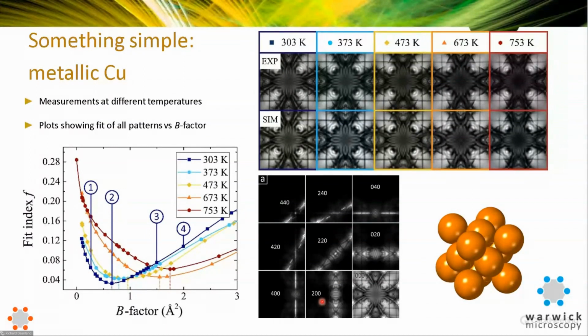And what happens when you change temperature, mainly in electron diffraction patterns, is that you increase the absorption. And absorption is very strong when you're aligned to crystal planes. Here you've got the 020 and 040 diffraction conditions lining up. And you can see as you increase the temperature, this just gets darker and darker. What's happening here is this is all turning into diffuse scattering in between the Bragg beams. And you can see we have the same kind of thing in simulation and experiment.